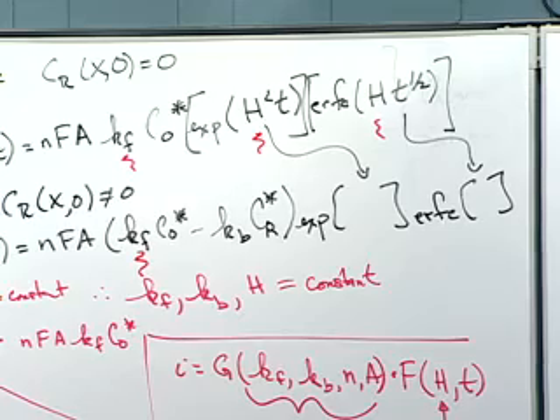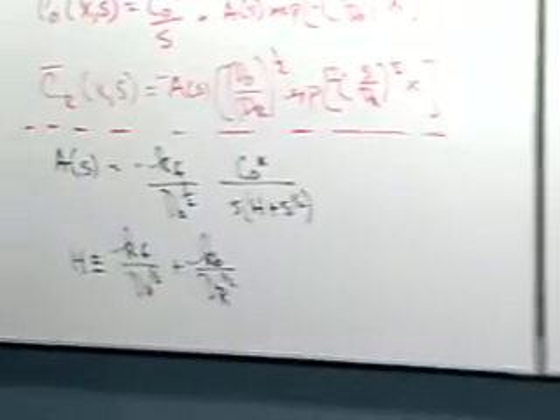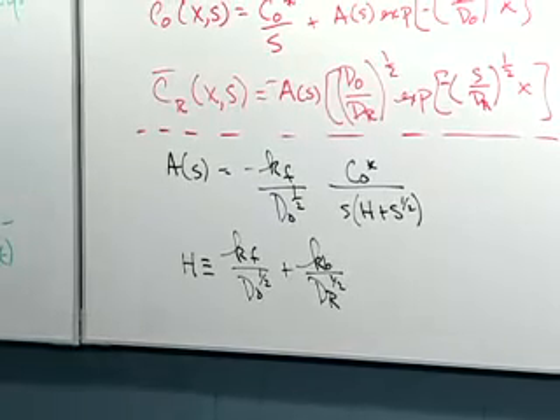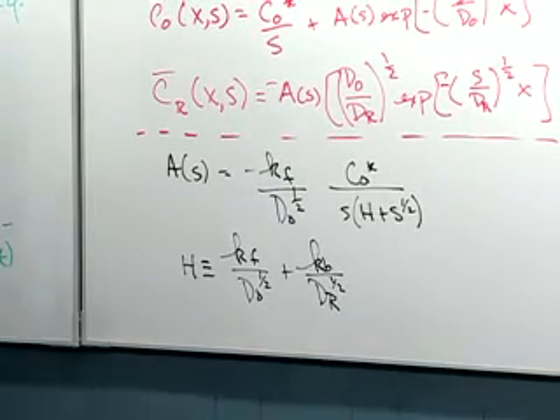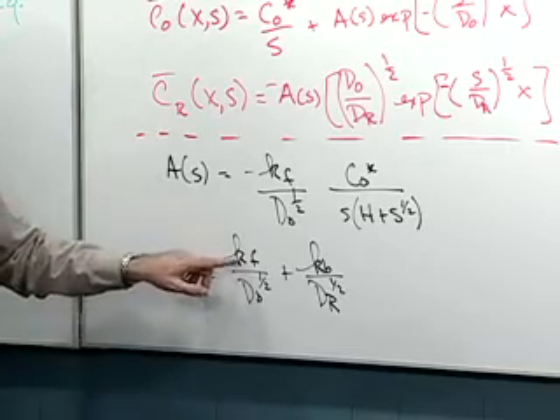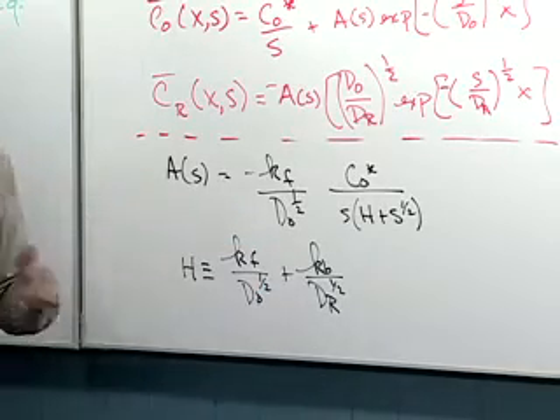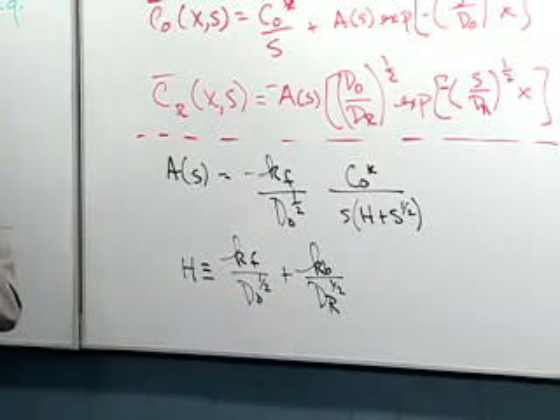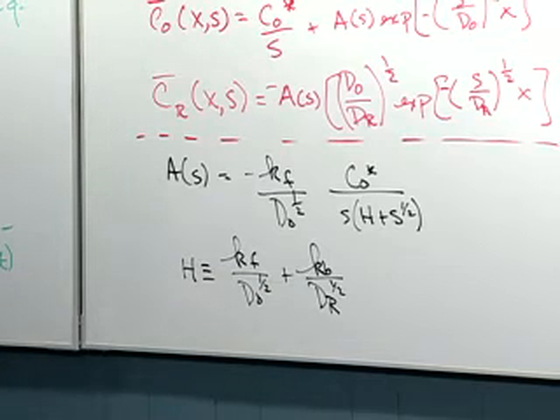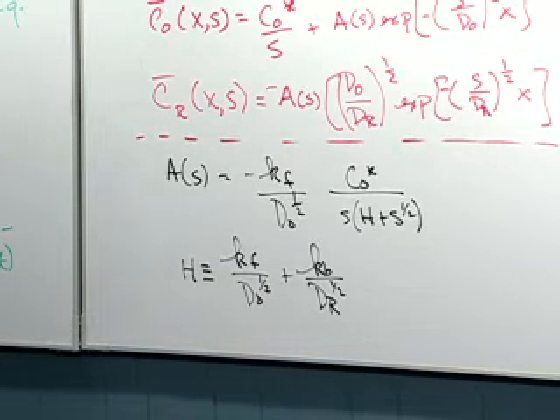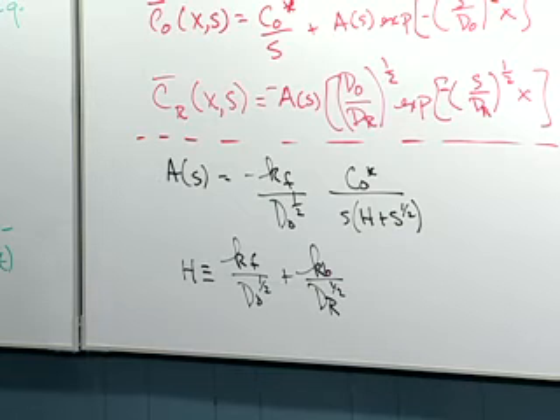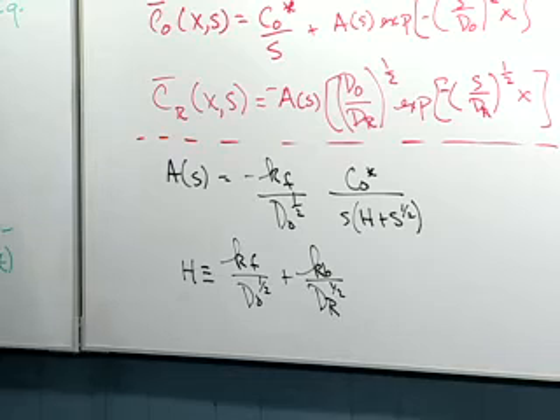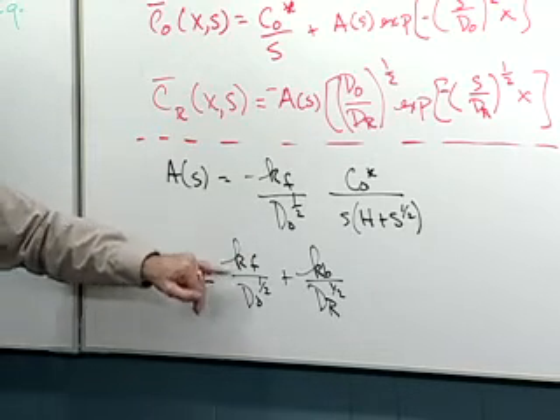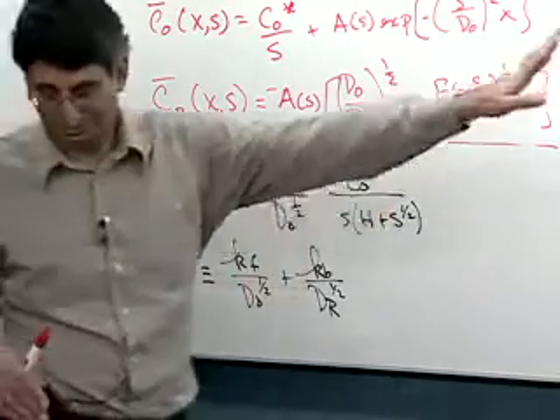The answer is more on the potential dependence of these parameters, and that is I can always find a potential, since I'm charge transfer limited, where these numbers are sufficiently small that I am dominated by the diffusion coefficients. So remember, this is not the situation where I'm doing a large potential jump, and therefore I become mass transport limited. I'm interested in this intermediate situation where I'm doing a potential jump where the rate constants are important. So if I pick my potentials correctly, my statement over here is a true statement. Okay.